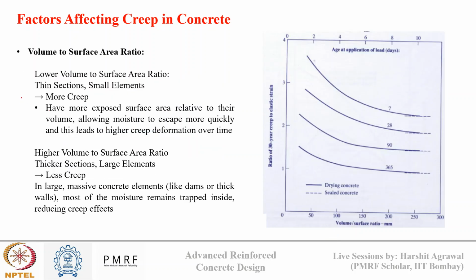Then influence of volume to surface area. So if we have a higher surface area, we'll have a lower volume to surface area ratio, and there we have more creep because more surface is exposed to the environment where more moisture loss can occur and higher creep deformation can occur. However, if this volume to surface area ratio is higher, there will be less creep, and that's why in dams and thick walls, mostly the moisture remains trapped inside and there is less creep effect in concrete.